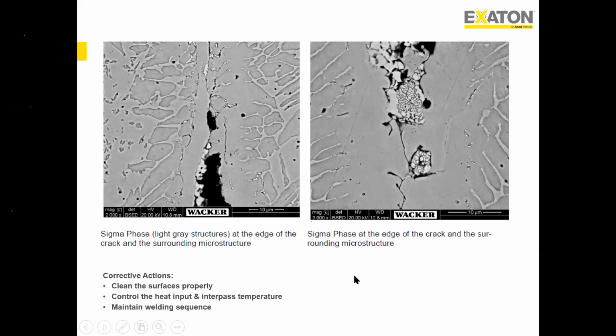And maintaining the welding sequence is also very important because with such a high thickness, and because of the coefficient of thermal expansion and contraction, they tried to go for one complete pass of welding, then reversed it and tried to weld the remaining. So it created a lot of residual stresses on the weld joint, and when they did the bending, it just broke out. So there were several factors that happened in this case. Yes, it was a fantastic case study for us, but really a nightmare for the fabricator. I had to spend a couple of weeks there to rectify this particular problem.